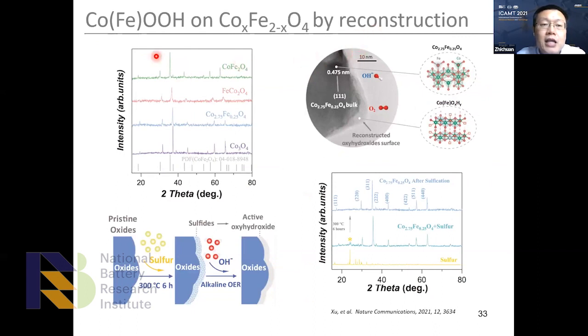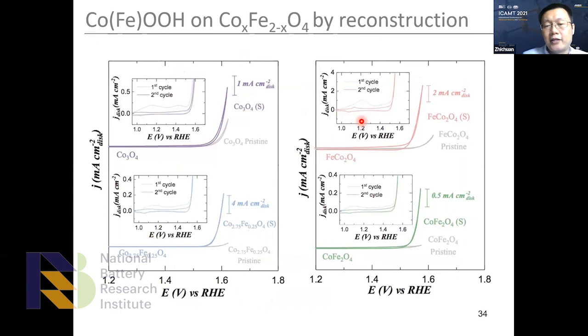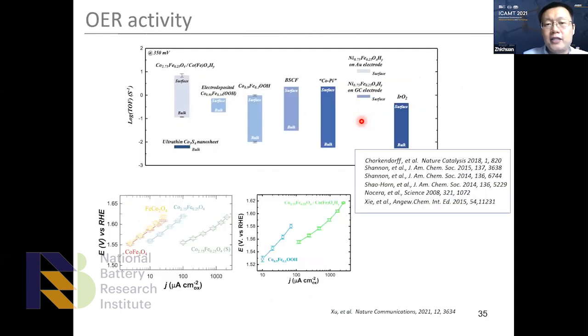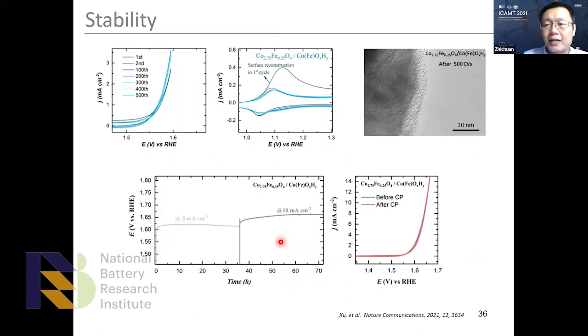We deposit cobalt iron oxyhydroxide on the cobalt iron oxide, which is a ferromagnetic substrate, and we have a paramagnetic top layer, which is a catalyst. And then we observed a much higher activity of this oxyhydroxide as compared to the oxyhydroxide without such a ferromagnetic substrate. So now, what is the reason that causes that? We found that there's an interaction between them.